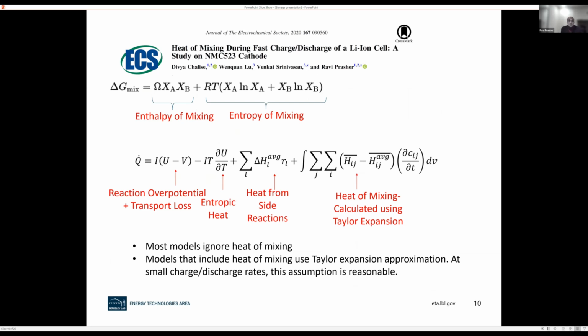very, very important, right? So if you look at, when you mix things together, there's something called enthalpy of mixing and entropy of mixing. Typically, we ignore the enthalpy of mixing. But here there is such a huge concentration gradient when you're doing fast charging that you cannot ignore the enthalpy of mixing. So the Q, the heat that is generated in a battery, has many terms.